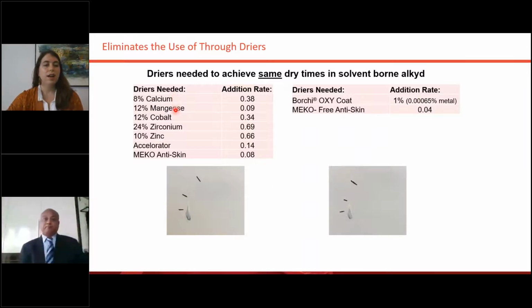It included manganese and cobalt. This is what we see with many customers trying to reduce their level of cobalt by adding carboxylate manganese into the system, but that really has a huge impact on the yellowing of the system. And of course, manganese carboxylate does not have the same curing efficiency and speed as cobalt, and not as fast, of course, as our Borchi OXY Coat or Borchy Dragon technology.